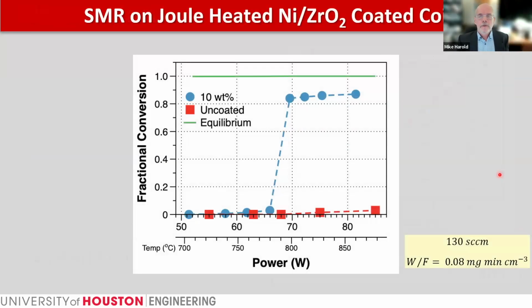So let me show you some results. Now, this is literally one of the first experiments that Elmer ran. This is for a 10 weight% nickel on zirconia support that's coated on a FeCrAl wire that's then subjected to a range of imposed power between 50 and nominally 90 watts. Along with the coated wire is the uncoated wire in the red squares. Now, the green line for this particular set of conditions is the predicted equilibrium conversion.